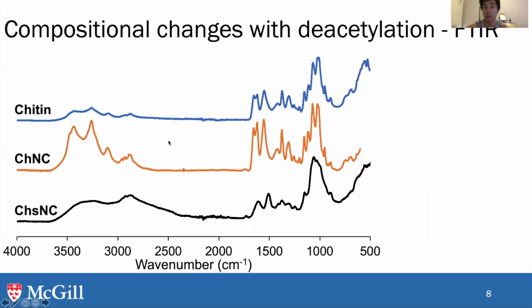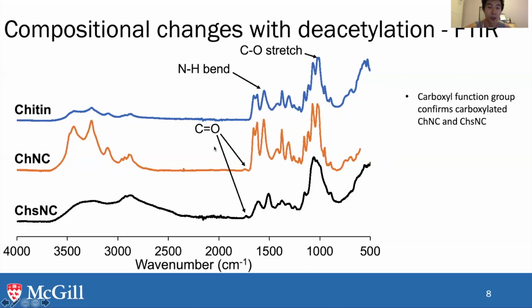Further, with structural comes compositional changes as well. So from chitin to chitin nanocrystal, one of the main things that we can see from the FTIR first and foremost are the NH bend here, as well as the CO stretch here, which we can plot a ratio of and find the degree of acetylation. So basically how many amines there are as opposed to acetamides. Another thing we want to focus on is the carboxyl COO bond stretch here. So we can see that after using ammonium persulfate as an oxidizing agent, of course, we see this C double O to confirm the carboxyl functional group. As well, we can see that with chitosan nanocrystal, similar to what we saw in XRD, there's a stark decrease in the number of defined peaks, further validating that we're losing crystallinity while we're doing this step.